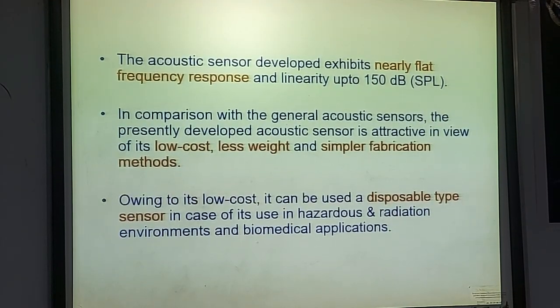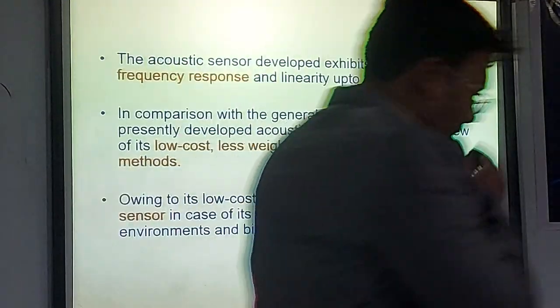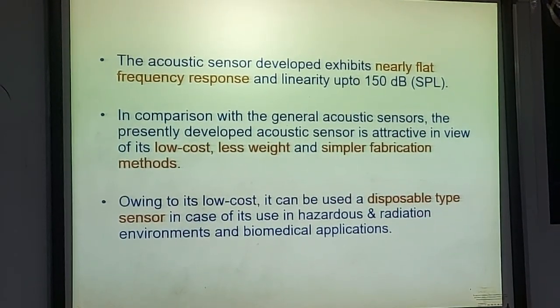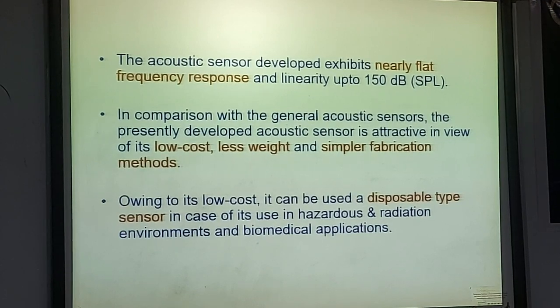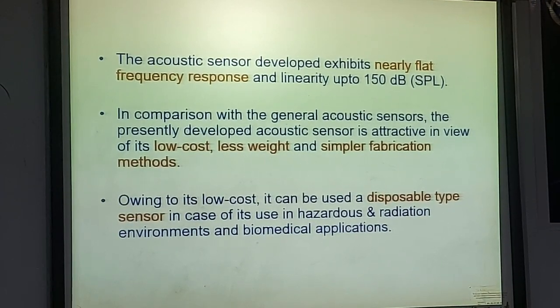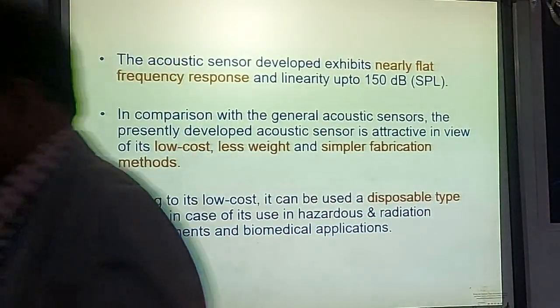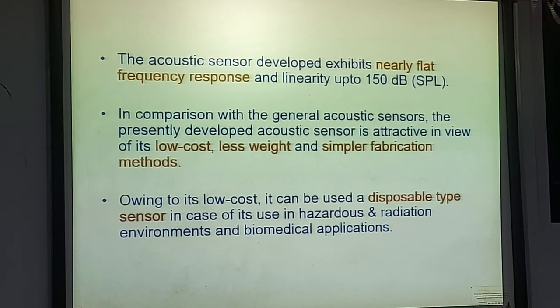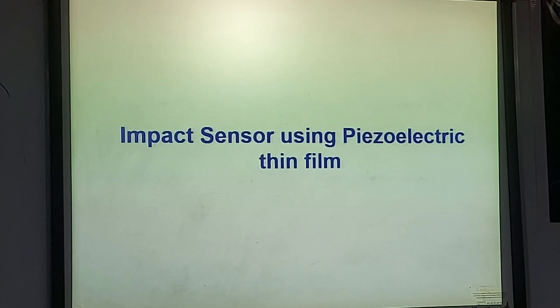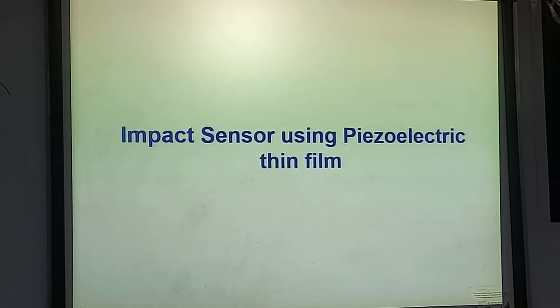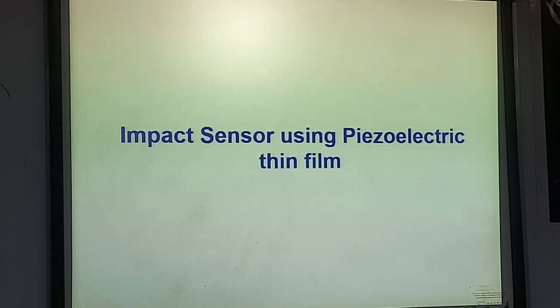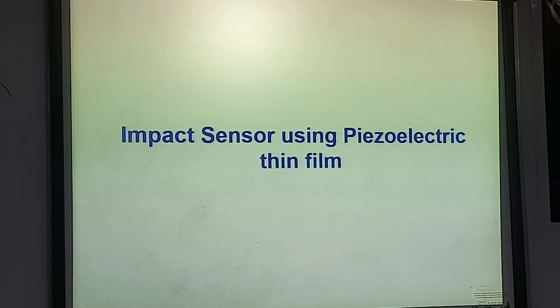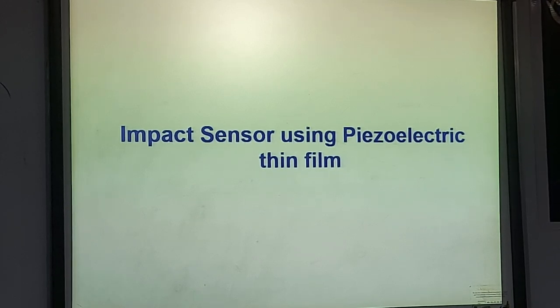So the acoustic sensor developed exhibits nearly flat frequency response and linearity up to 150 dB sound pressure level. In comparison with the general acoustic sensor, the presently developed acoustic sensor is attractive in view of low cost, less weight and simpler fabrication methods. When it is low cost, it can be used as a disposable type sensor in case of its use in hazardous and radiation environments, as well as in medical applications. In fact, the same kind of piezoelectric thin film, if we use on a silicon substrate, we can make a MEMS-based acoustic sensor, which is very much there in the market.